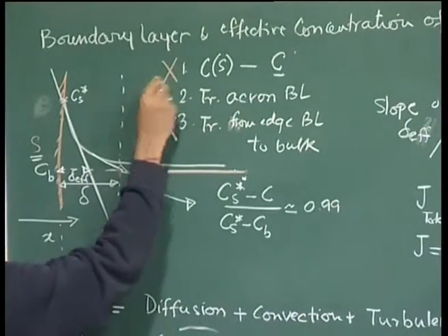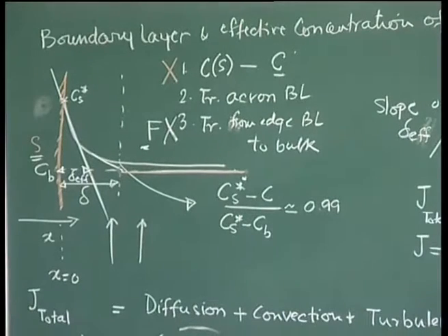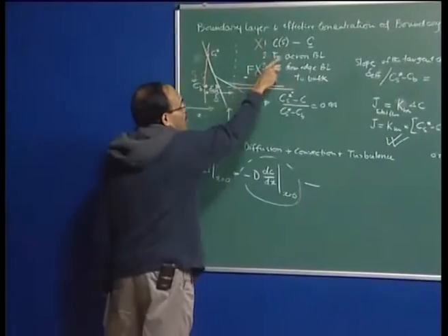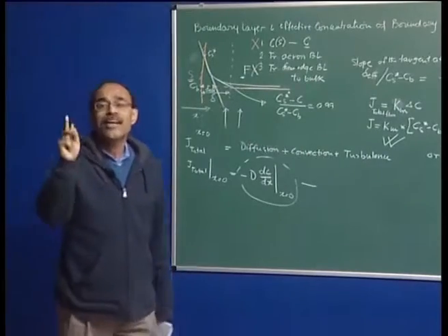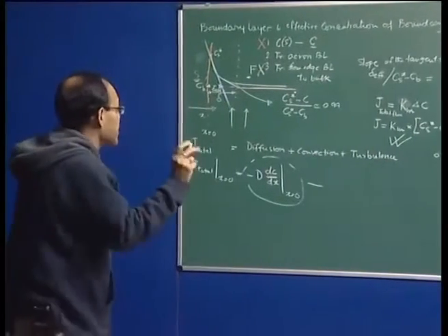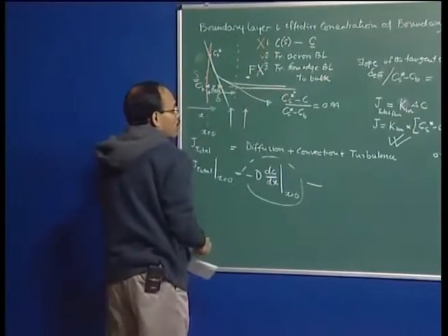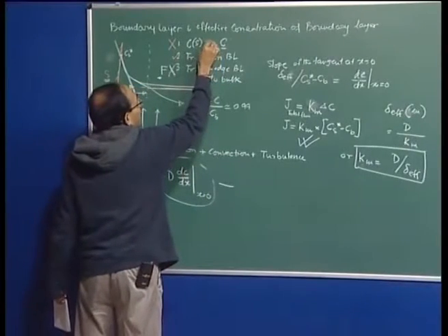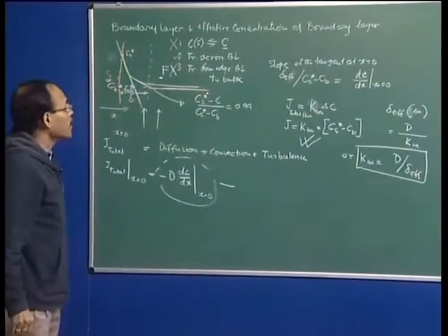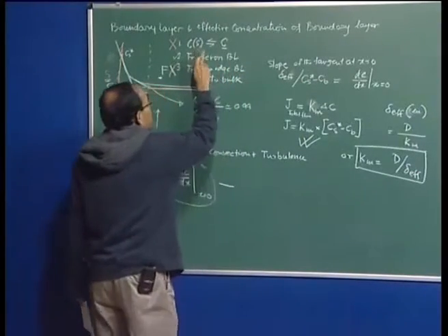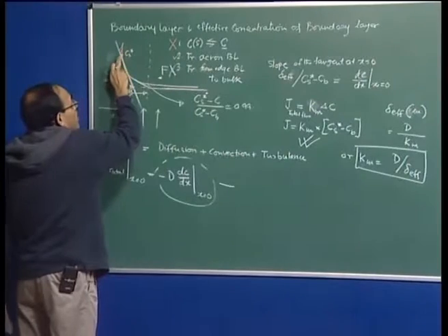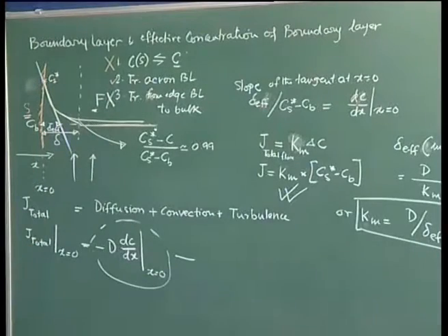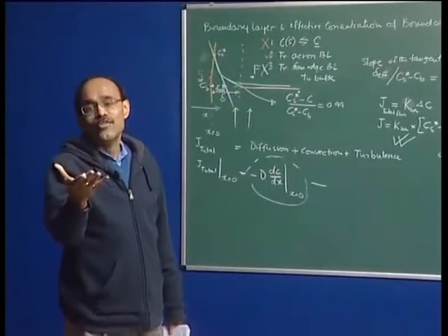If I say that this chemical reaction, the interfacial reaction, is also very fast relative to this, I am essentially saying that the dissolution is controlled by transport across the boundary layer, or boundary layer mass transport is the rate limiting step. In that case, this chemical reaction becomes, therefore, I can complete the arrows and say this is at equilibrium. This equilibrium essentially implies that we have reached the equilibrium concentration of the solid at the surface. And what is the equilibrium concentration? In this case it is nothing but the saturation concentration of the species.